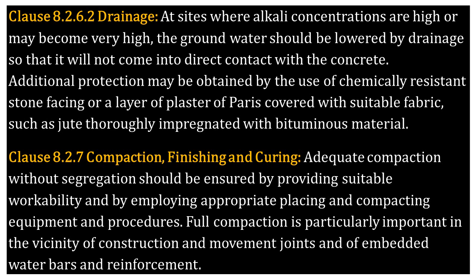Now it is clause 8.2.7, compaction, finishing and curing. Adequate compaction without segregation should be ensured by providing suitable workability and by employing appropriate placing and compacting equipment and procedures. Full compaction is particularly important in the vicinity of construction and movement joints and of embedded water bars and reinforcement.